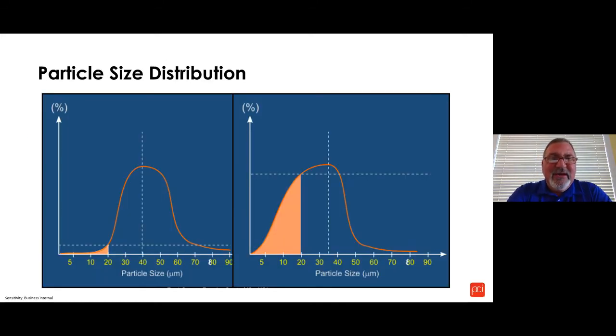Particle size distribution: there's an analyzer that measures particle size in a powder formula. There's not just one size of powder grain. There are actually different sizes inside a box of powder, and it looks like a bell curve. The one on the left is virgin powder, powder that's come straight out of the box. It hasn't been sprayed. You can see that the fines, less than 10 micron, are pretty small. The sweet spot for applying powder is up here, everything above this line.